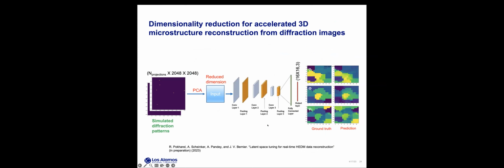So as an initial attempt to tackle this problem, we represented these high dimensional detector images as a few principal components, which were then used as inputs to predict the full field orientation distribution in a single calculation. And here's an example result for the simulated data. The column here on the right is the CNN predictions, and the column here on the left is the ground truth for the three different Euler angles. And you can see that the model does a decent job. It's not perfect, but it does a decent job in reconstructing the spatially resolved microstructure.